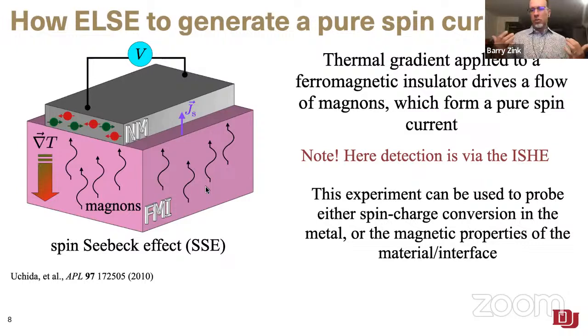Those magnons are also carrying spin information. They're carrying angular momentum, and so they represent a spin current as well. So this spin current in this ferromagnetic insulator is launched in the material. It's there. Now you just need to measure it. The typical way to measure it in this experiment that is called the spin-Seebeck effect, or specifically the longitudinal spin-Seebeck effect, is to then use that inverse spin Hall effect that I mentioned as our way of converting that pure spin current into a charge voltage that we can actually measure with a voltmeter. So that's what's happening here.